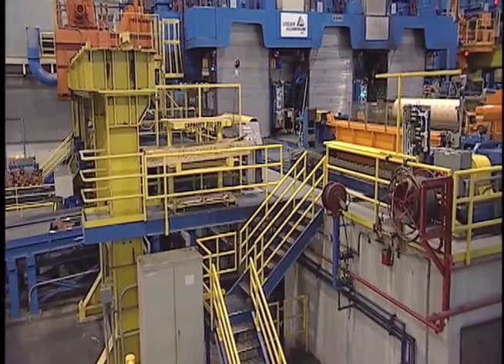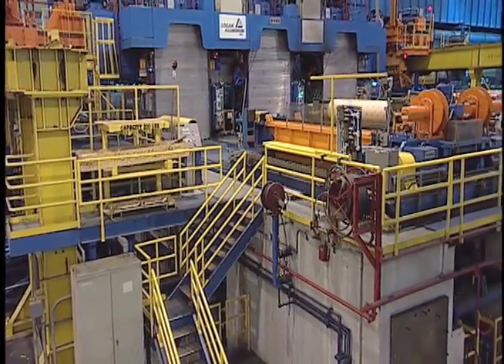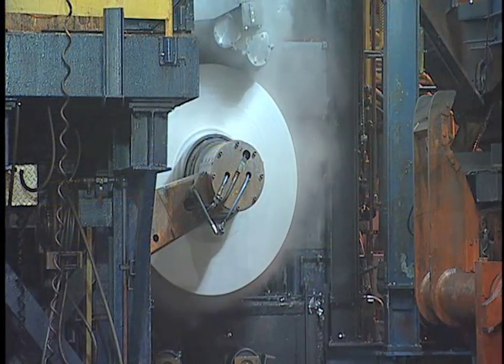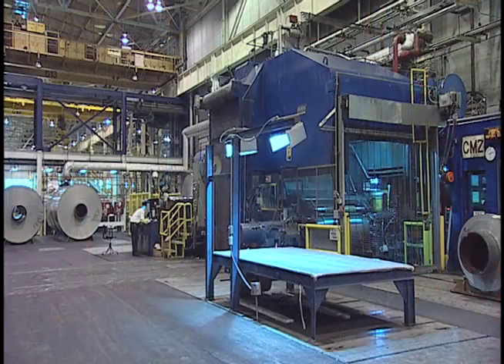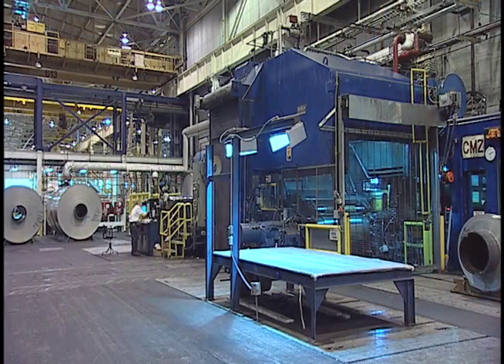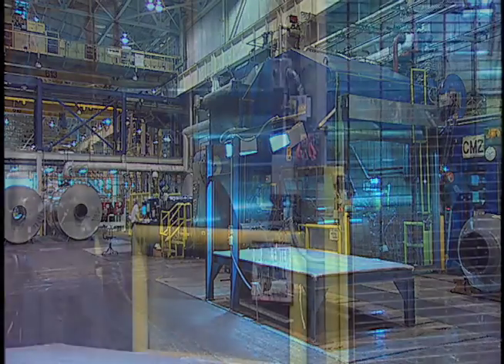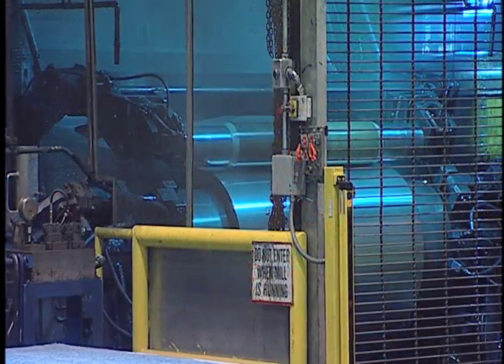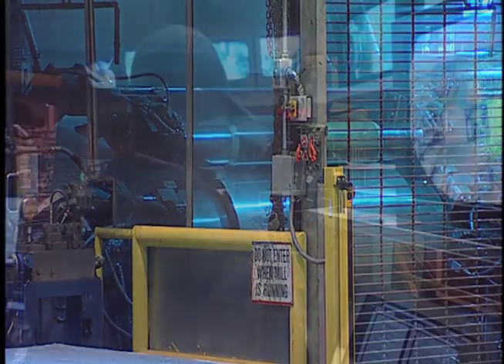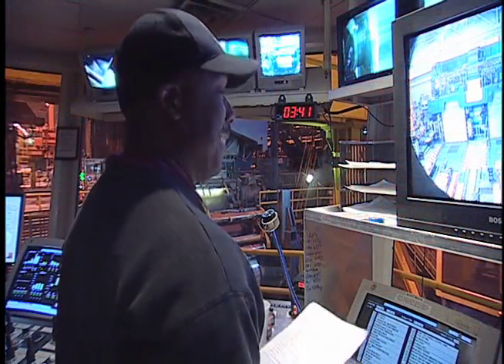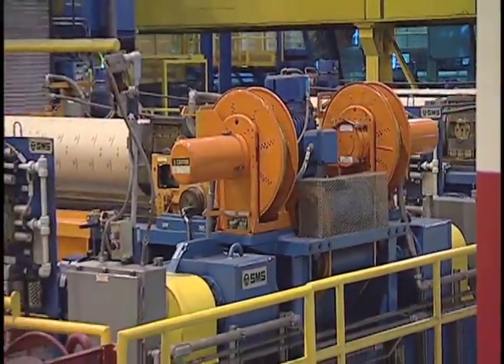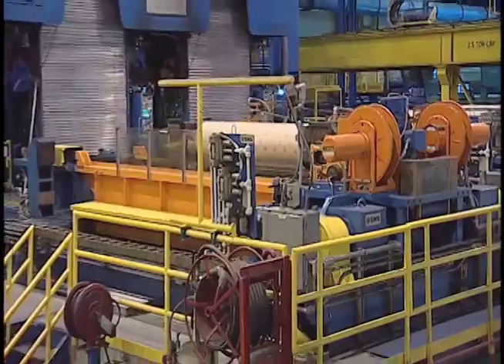Depending on the metal composition and required gauge, a coil could have gone from 1 to 5 passes on the mills. CM1 can take 3 to 5 passes from the breakdown stage to finish pass. CM2, originally designed as a foil mill, completes 1 to 2 finish passes on coils. CM3, a 3-stand tandem mill, can take a coil from breakdown to finish gauge in 1 pass.